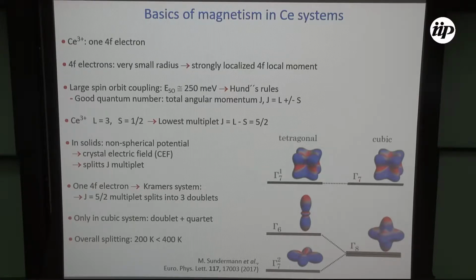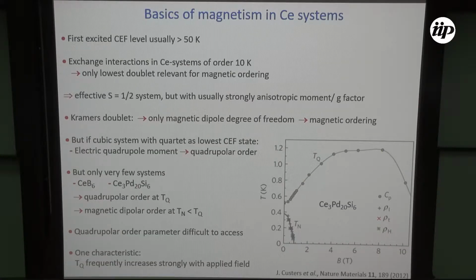In the case of tetragonal symmetry, for example, there are these wave functions, but they depend strongly on the real structure of the system you are looking at. The first excited crystal field level is usually above 50 Kelvin, usually in the range between 100 and 200 Kelvin. The exchange interactions are weaker, so typical magnetic ordering temperatures are only 10 Kelvin. This means that if we are interested in magnetic ordering phenomena at low temperature, only the lowest doublet is relevant, and therefore one can analyze most of the low temperature properties of cerium systems using an effective S equals 1/2 system with a usually very anisotropic moment or g factor.